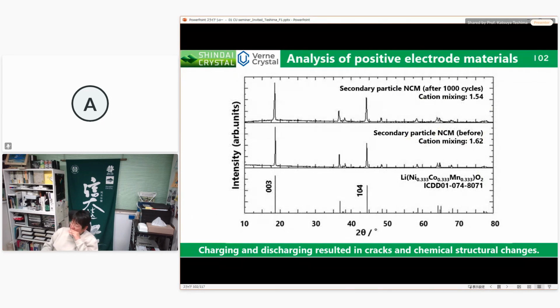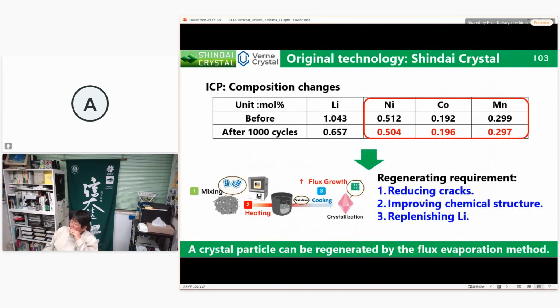After 1000 cycles, chemical structure deterioration occurred, as shown in these XRD pattern figures. After 1000 cycles, lithium dropped by 35%, while other materials remained.